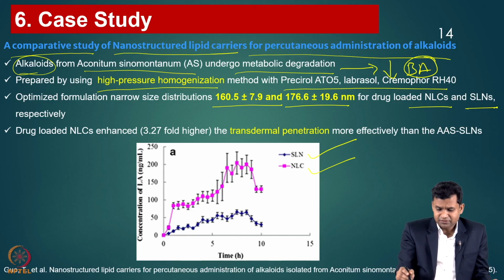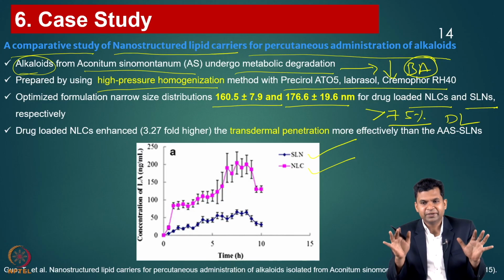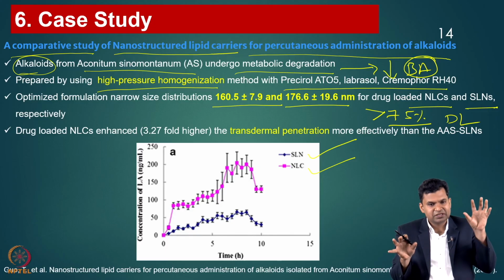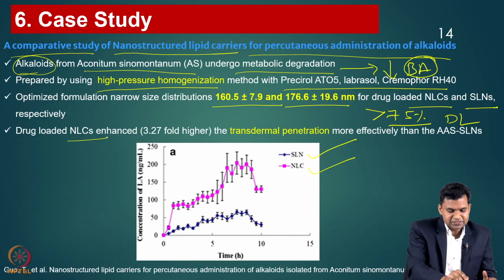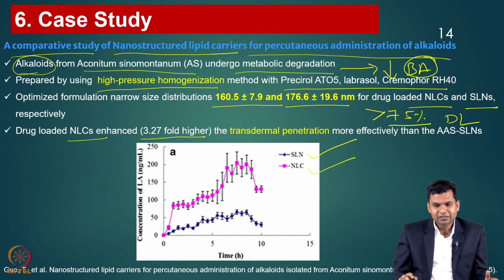Now, they got more than 75 percent drug loading, and after that they observed the penetration of the drug-loaded molecule. They compared these molecules in two carriers. One is SLN, second is the NLCs. So the drug-loaded NLCs enhanced penetration 3.27-fold higher compared with the SLN formulations.